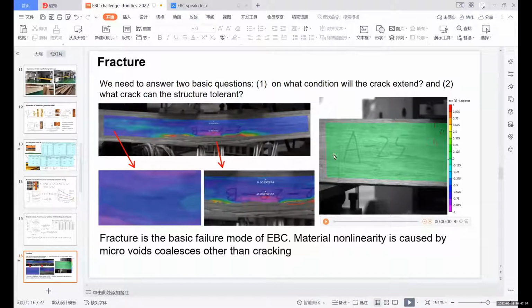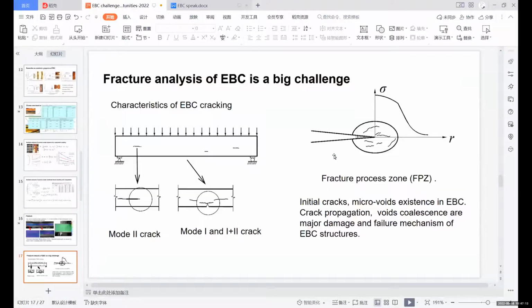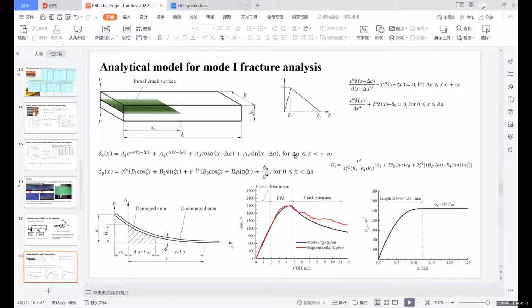So EBC fracture presents conspicuous nonlinearity. In the crack tip front, the evident fracture process zone can be seen. In this zone, many fine cracks are generated and fiber bridges can be observed. So the constitutive relationship of the material no longer obeys Hooke's law. So the stress intensity factor cannot be used to measure the fracture property of EBC. So the fracture energy is adopted to measure the fracture property of EBC cracks.